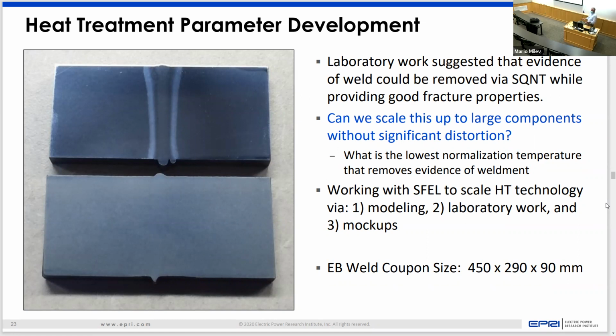So if I remove that weld, do I really need to inspect that at 10-year intervals? Normally I inspect every weld in a reactor vessel in 10-year intervals. Will I have to inspect this now? So the question is, can we develop this for very large components such that we can heat treat them without distorting the component? And then we go to the NRC and basically get them on board with helping us to eliminate inspection of these components, because this will now be one solid structure with no weldments in it. Can't see the weldment, where is it? So that's what a lot of this technology is focused on right now.